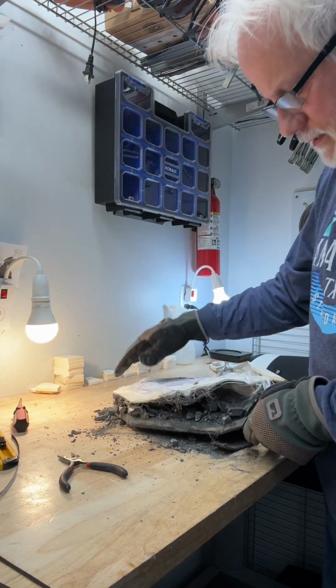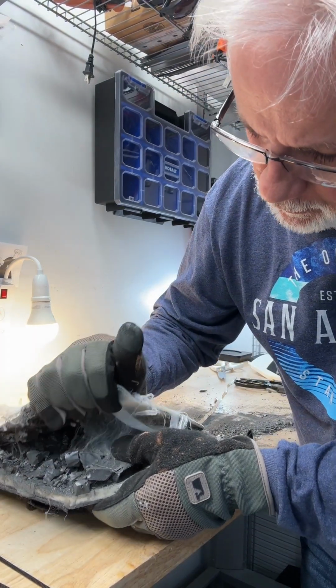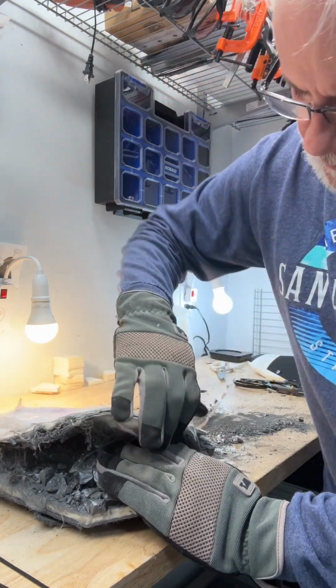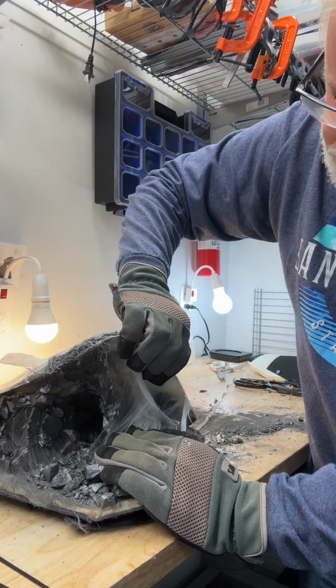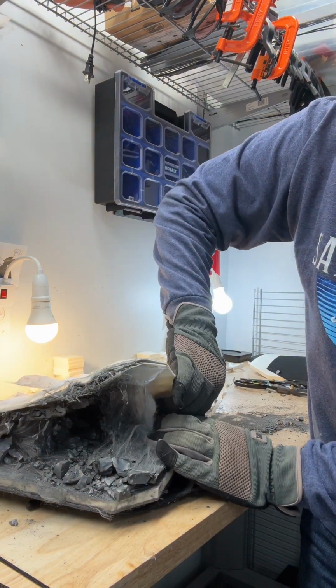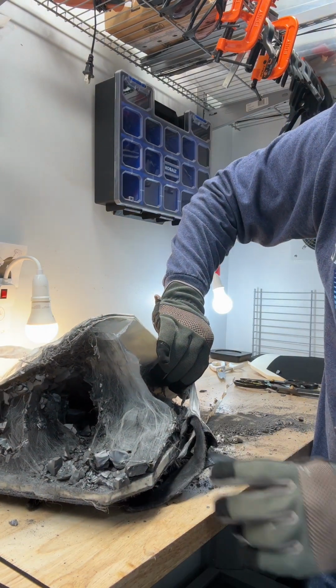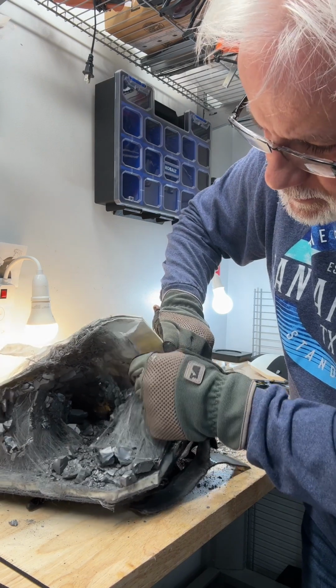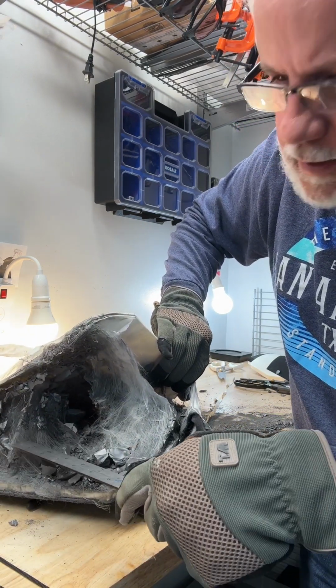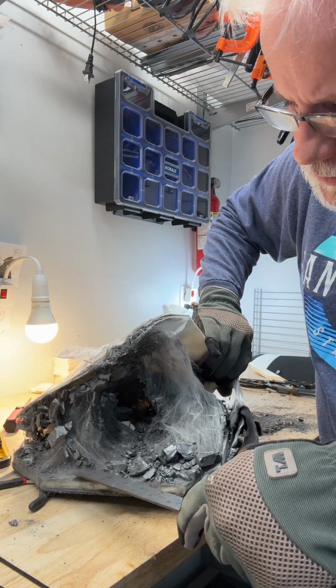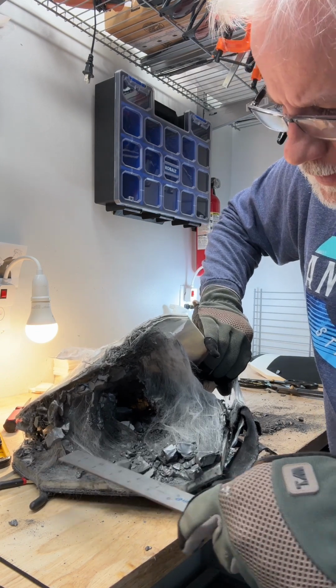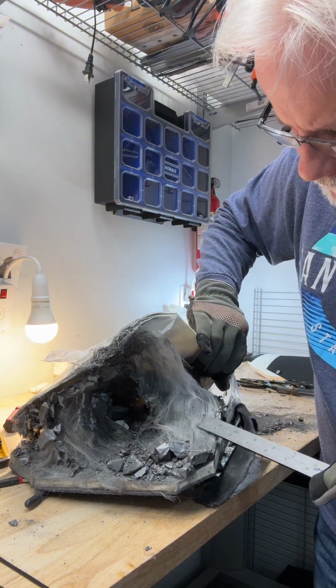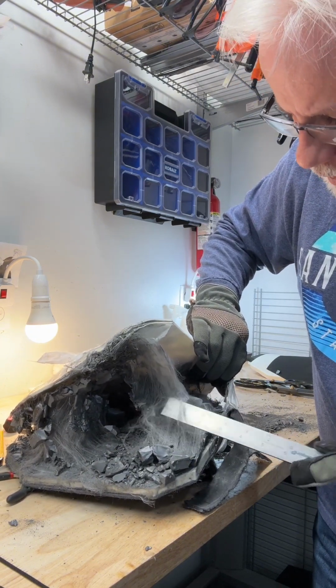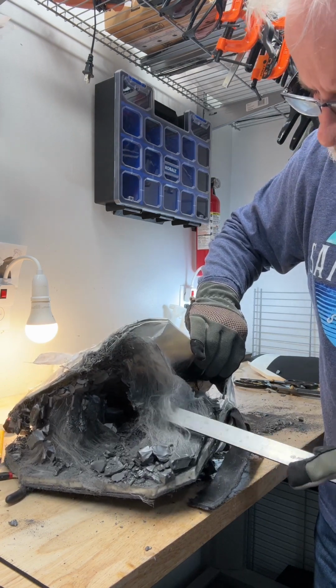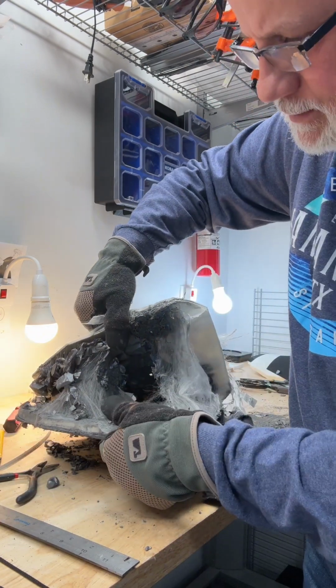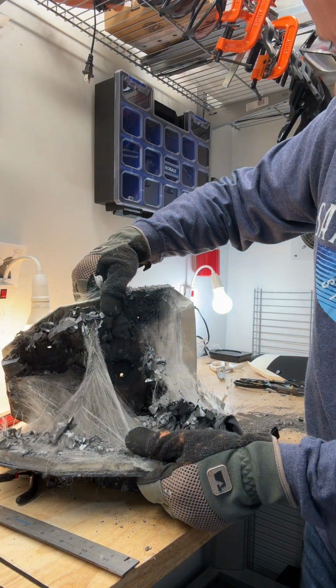Now I'm going to change the camera angle and see if I can pull this cover off of here. It's obviously the ceramic is destroyed in here, so it's difficult to pull this off without absolutely destroying the remaining ceramic. So you can see the effectiveness of the adhesives in here. This is the composite cover. This is what's hanging on in here. All this fiber you see in here is the result of a good adhesive still grabbing onto that silicon carbide ceramic. That silicon carbide's a little bit different than aluminum in terms of the stickability of the adhesive properties, and so our adhesives will work with the aluminum oxide, the alumina, and the silicon carbide. As you can see here, it's extremely good adhesion.